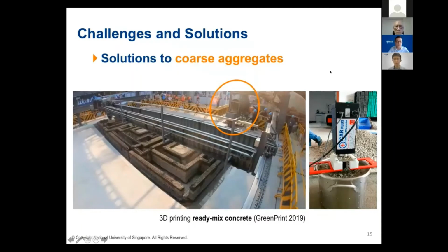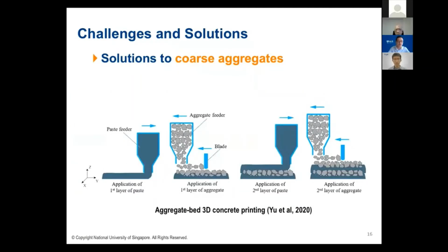It's still very challenging. Okay, here I want to introduce my work. This is done by my PhD student, Mr. Yu Shiwei in Melbourne. We introduced the aggregate bed 3D concrete printing. We extrude paste onto aggregate bed. Okay, so we extrude one layer of cement paste or mortar. Then we spread one layer of coarse aggregate. So the aggregate can be bound by the cement paste.